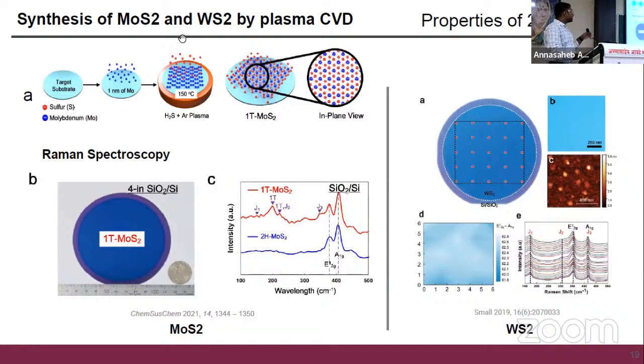Typically in plasma CVD, we grow these kinds of 2D materials. Here we are showing the 4-inch wafer synthesis of these 2D materials, the MoS2 or WS2 synthesis grown in our lab, which we also published in other papers. Typically we take our substrate and deposit some metal layer. In case of MoS2, we deposit Mo; in case of tungsten, we deposit tungsten. Then in the plasma chamber, we sulfurize it using sulfur plasma, and eventually it forms the MoS2.